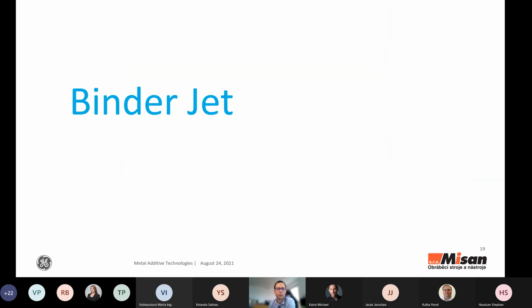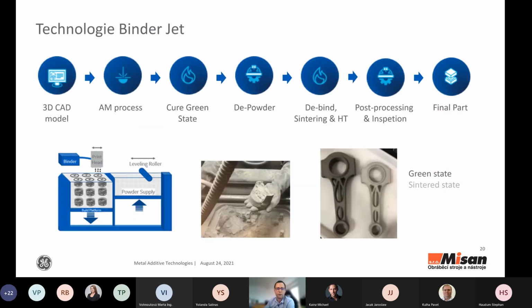It's not so important. The last is the binder jetting technology. It's actually the youngest of the technologies. It's in preparation. So what is this technology about? Still, we have a metal powder. We still layer the powder in thin layers. But we don't use heat to melt the powder. Here we just put binder with the print head on it, just to glue the powder together. And then we take out these parts and put them into a debinding and sintering oven.